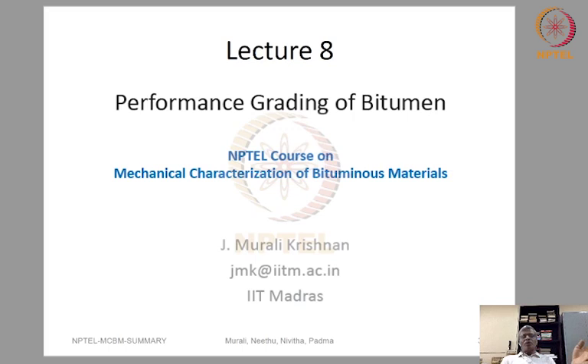Then what we did was we stepped on to performance grading of bitumen. Now, what really is the issue related to viscosity grading of bitumen? In viscosity grading of bitumen, you make measurements at a fixed temperature, 60 degree centigrade. Now, what if the geographical location in which you are going to use it does not have a critical temperature of 60 degree centigrade? What you might really want to ask is, I am not really interested in the performance of the material at a fixed temperature, but I want zero rutting at the critical temperature in my geographical location. So what it means is, you should first identify the parameter that you could prescribe for rut resistance or fatigue, and then check whether those values will be available at your critical location. So this is really called performance grading.